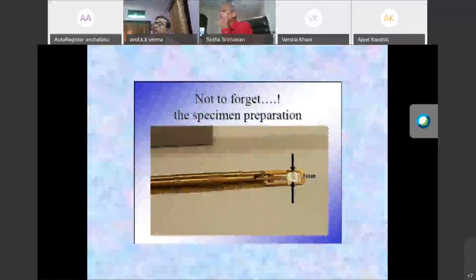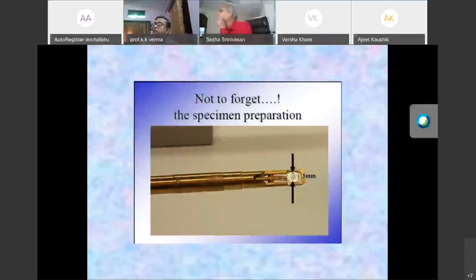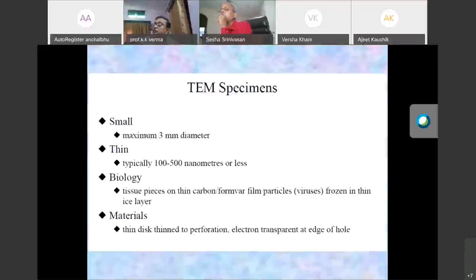So this is a specimen rod. On top, you can see a very small circular part where you put your things, which is called a grid. And on the grid, you put the sample. So this is the specification of the grid. The grid has a mesh, 300 or many meshes, and this is 3 millimeter in diameter, made of copper, gold, and many metals, depending on non-magnetic materials. So many kinds of TEM grids are available, and this has a lot of mesh.